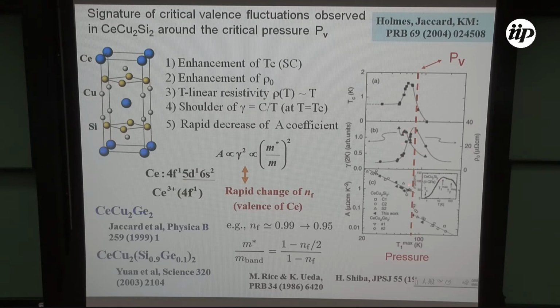Well, of course, gamma decreases, and some structure appears. There is a rapid decrease of the A coefficient at this pressure. That means m star, due to the so-called Kadowaki-Woods relation, m star over m decreases rapidly. And according to the canonical formula of Rice, Ueda, and Shiba, nf changes rapidly, say from 0.99 to 0.95 here.